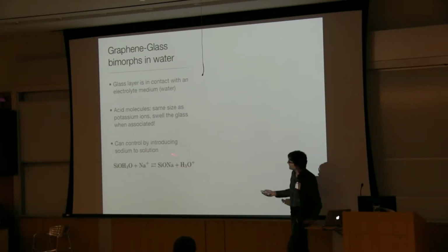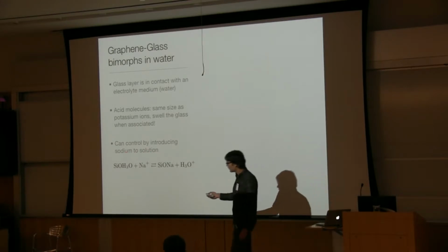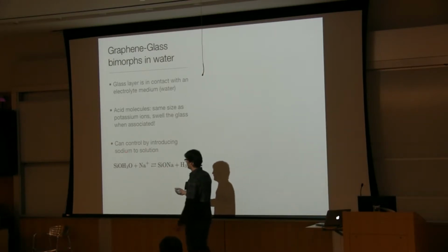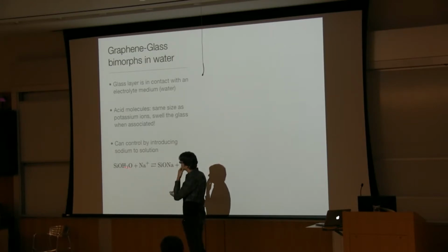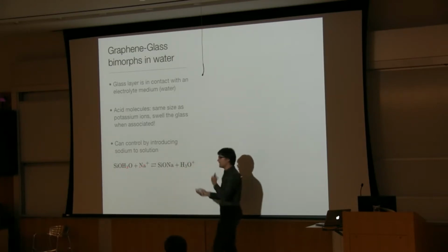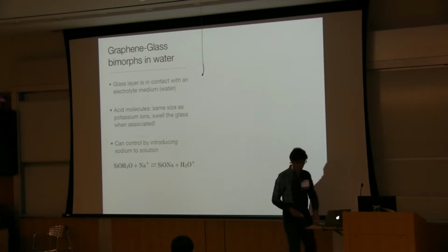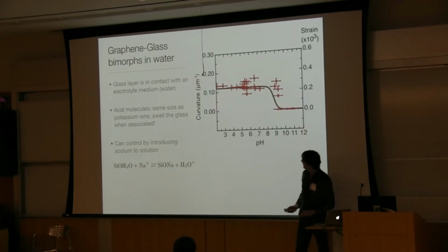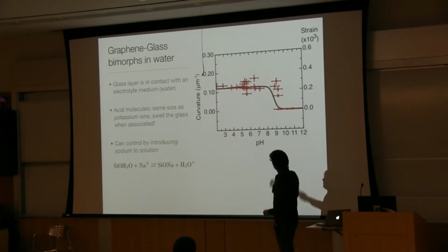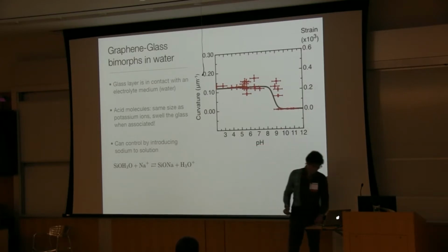And this also implies that this is a mechanism that can be controlled, right? Before, I pushed out the sodium by putting in the potassium. Here, if the swelling is due to the acid molecules, I could drive them out by putting sodium back into the solution. And so that's what we did. Here we just raised the pH by adding sodium hydroxide, so simultaneously we're decreasing the amount of acid molecules as we're increasing the amount of sodium, and lo and behold, that finite curvature from the previous graph drops off at a critical pH value around 9.